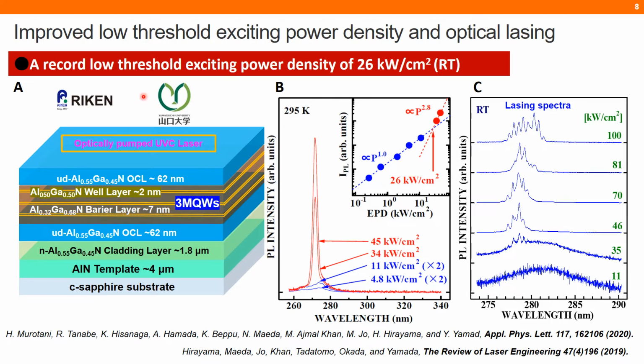Ultimately, the threshold excitation power density was improved. A record low threshold excitation power density of 26 kilowatt per centimeter square at room temperature was achieved, and lasing spectra at room temperature were also observed in optically pumped laser diodes. This work is published here, and some discussion is also given in this paper.